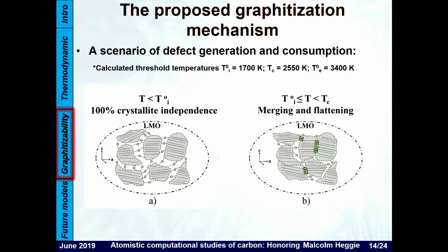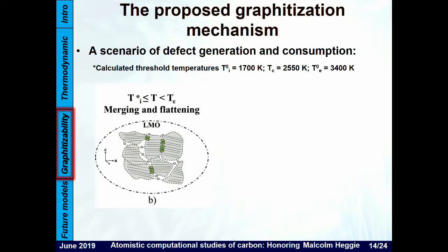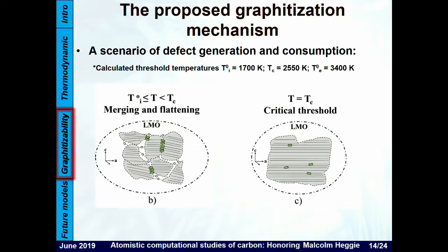Then, as you heat it up, the density difference between the intercrystalline matter and the cold crystalline phase will start to diminish. As it does, defects will be generated at the interface between the crystallites. These defects are called ATD in the sense that these defects are not frozen. When they are heat treated, they will be able to be removed, and as they are removed, they will induce graphitization in the sample.